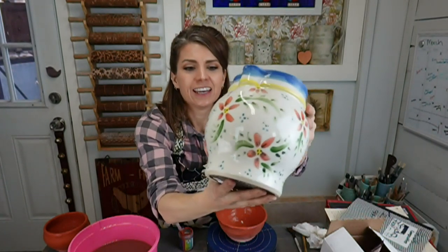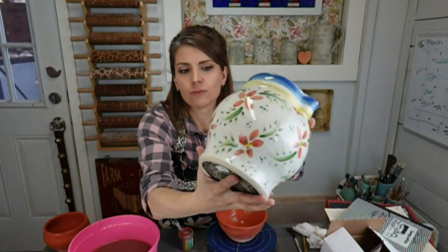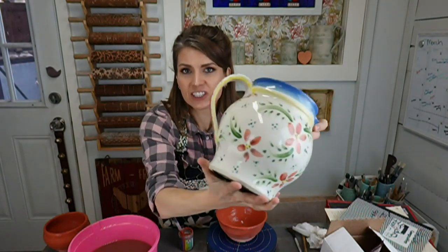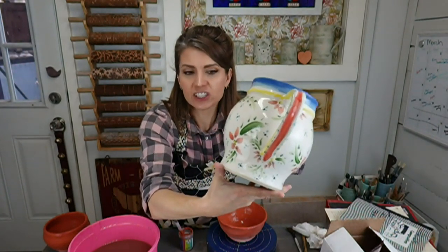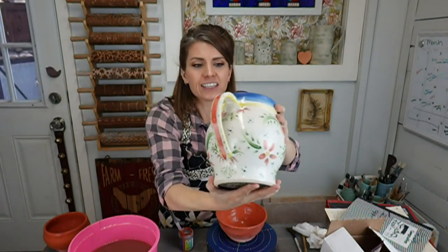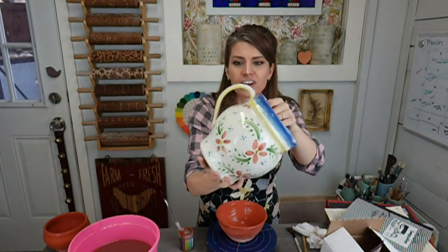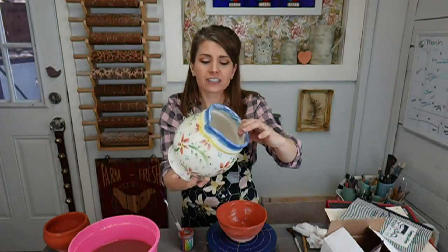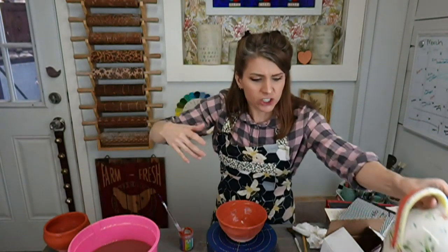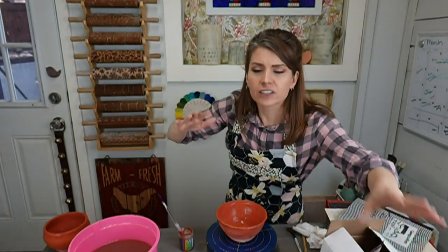And you can see the underglaze will melt into the glaze, and it is really a nice way to do a decoration if you want to do a painterly decoration on top of a glaze. It's just another way of decorating your pottery. The blue did flux a little bit, but if we look at the sides, it didn't really flux on the little blue dots. So it shouldn't move too much. It should stay pretty stable, but you might get a little movement on the blues, sometimes on the black too, because it has cobalt in it.